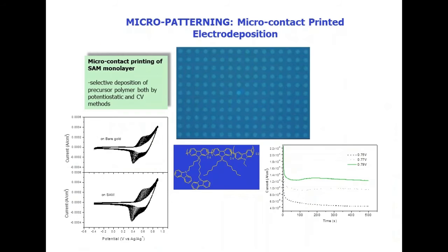So we started basically by demonstrating that we can pattern materials using microcontact printed electrodeposition. In this case, these are blue emitting materials that were patterned by microcontact printing and then deposited directly on the surface such that we can have a micro LED device. And that means that the polymer here can be used perhaps in the future for micro displays.